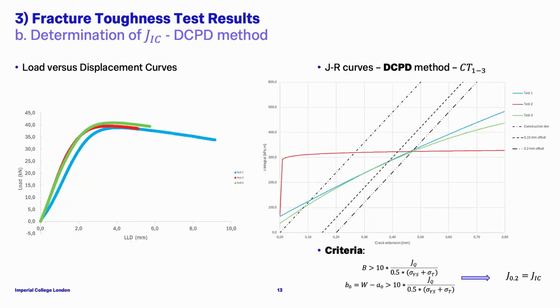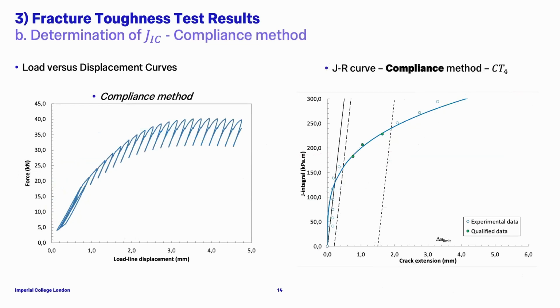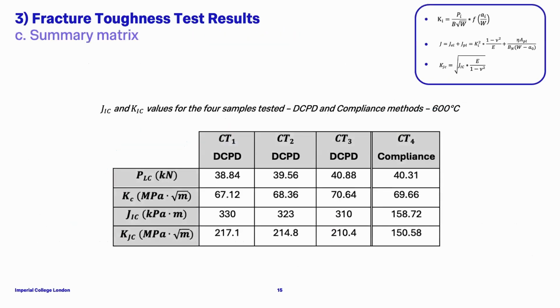And here are my first three JR curves. They all give a JIC value around 315 kilopascal meter, and so they all seem to agree. My fourth test was using the compliance method, more particularly the unloading elastic compliance method. And after 21 cycles, here's the JR curve I obtained, with a much lower JIC value, around half of what we found just before, around 150 kilopascal meter. And this is the summary matrix with all the results of my four tests.